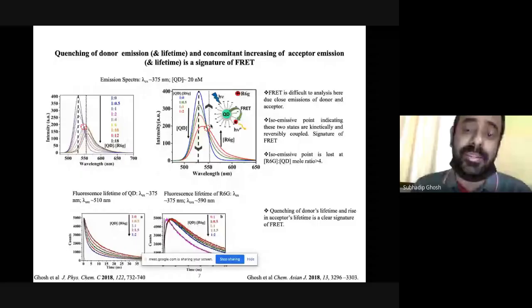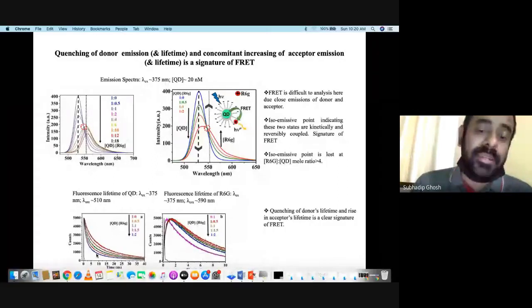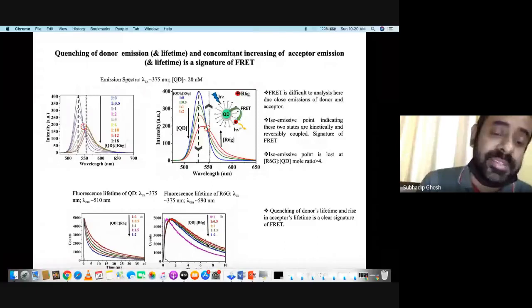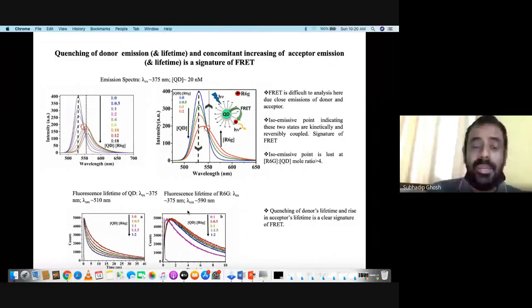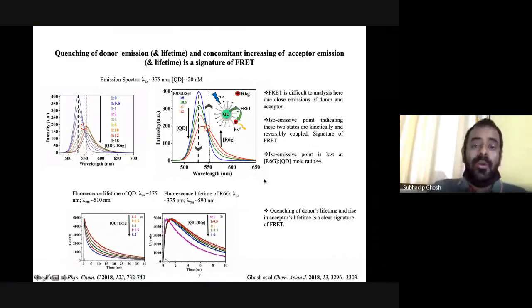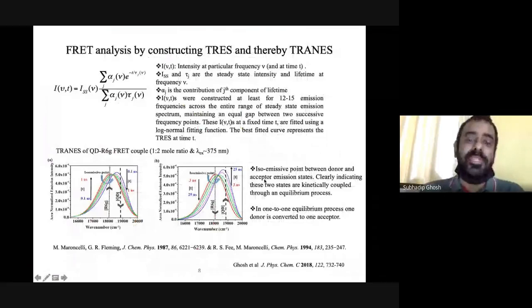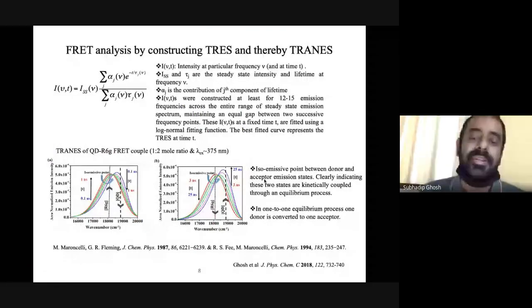And now if we look into the fluorescence lifetime profile, which we measure in TCSPC, we found that donor emission is quenched at the cost of a rise coming in the acceptor's emission. This rise indicates again that FRET is taking place. So next we did time resolved emission spectra. Steady state emission spectra is an equilibrium process, but now we see the emission spectra at different times. That is possible in a TCSPC instrument, and with some post-treatment of the lifetime profile, we are able to generate the emission spectra of the molecule at different times.